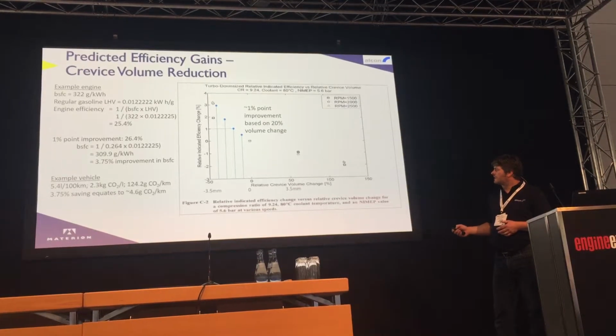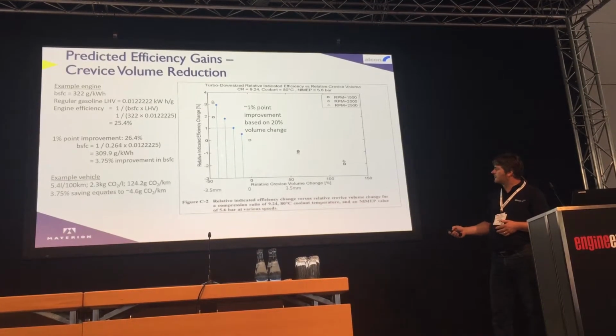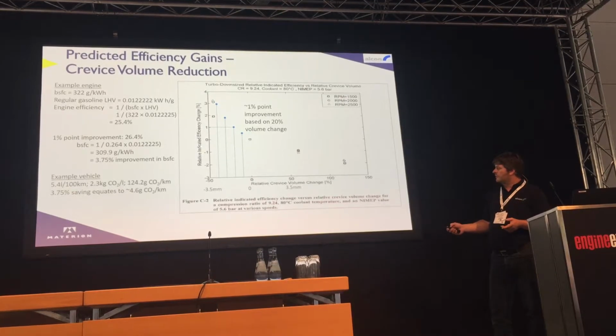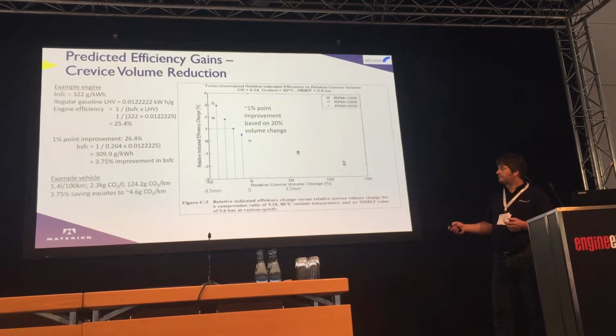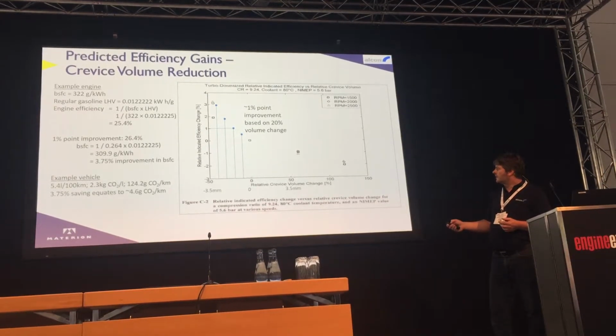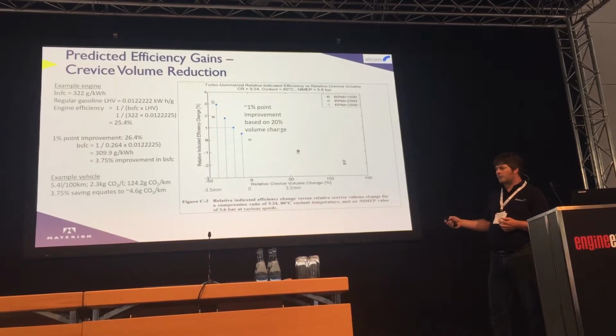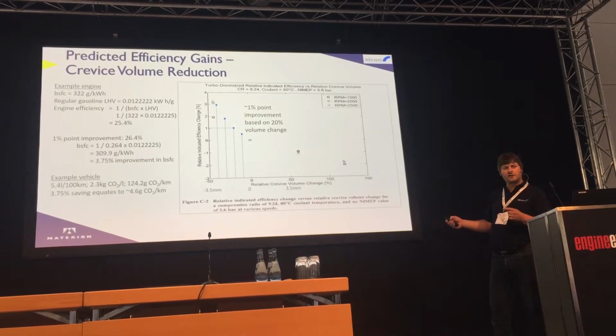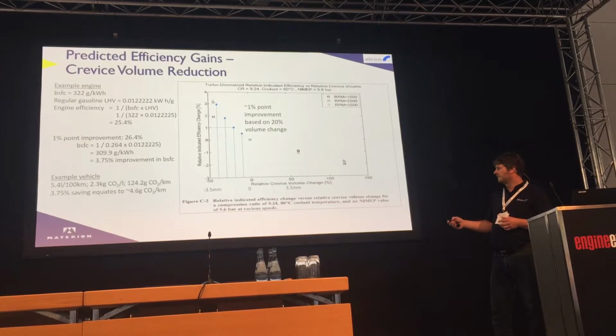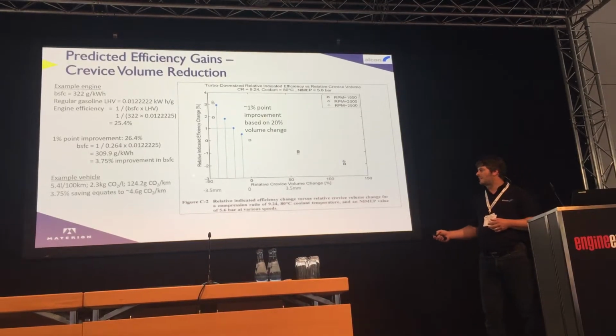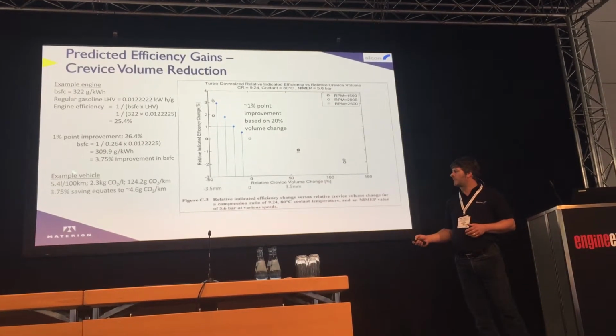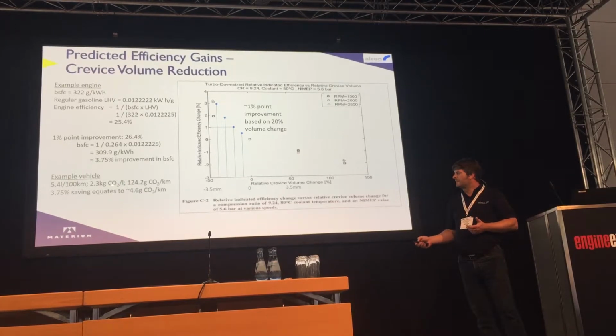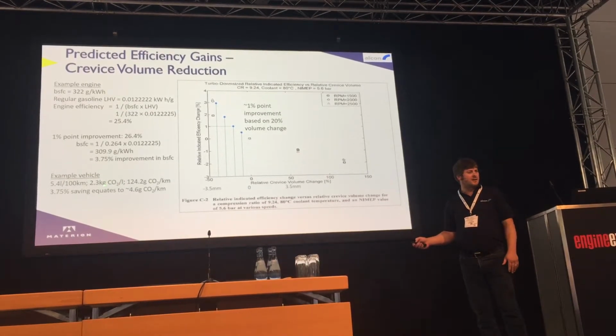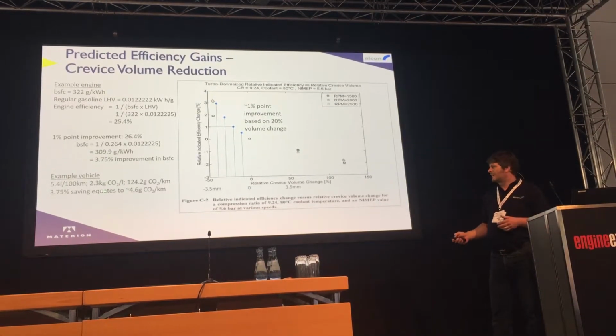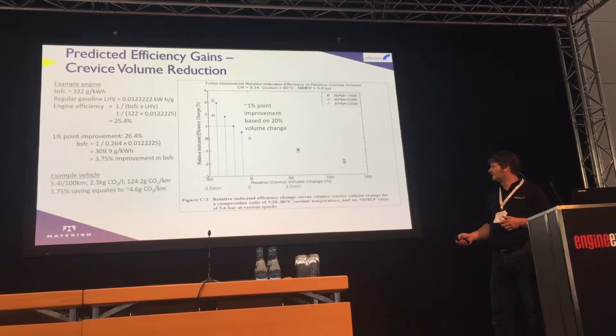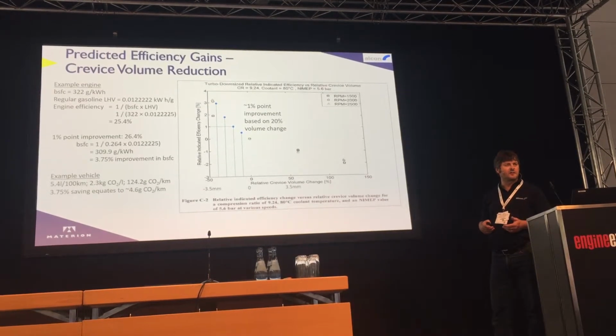And as you can see, it's very sensitive. So this graph here shows the relative indicated efficiency change. So a 1% improvement was gained by a 20% change in the crevice volume. So it's a significant number. If you equate that, again making some assumptions, back to a vehicle, 4.6 grams of CO2 per kilometre, it's again a very, very significant number, all from a change in crevice volume essentially.